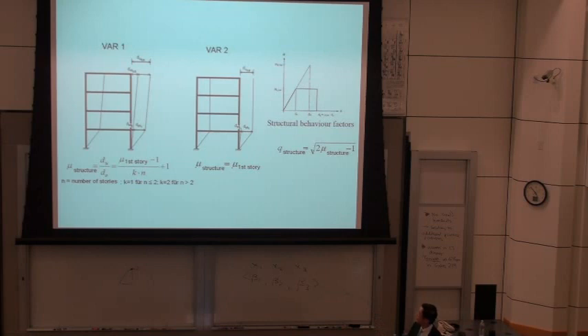In the first alternative, you have the elastic displacement, then the plastic displacement at the first floor. Then it goes up parallel to the elastic displacement. So you say that the ductility of the structure, mu, is nothing else than the ultimate displacement over the elastic displacement. And we take the ductility of the wall test, of the cyclic shear test, as the ductility of the first story, minus 1, over k times n, where n is the number of stories, and k is equal to 1 if you have less than or equal to 2 stories, or if you have more stories, k is 2.